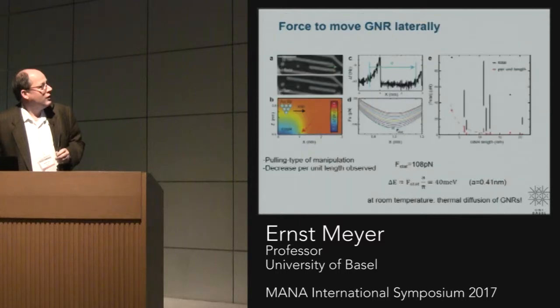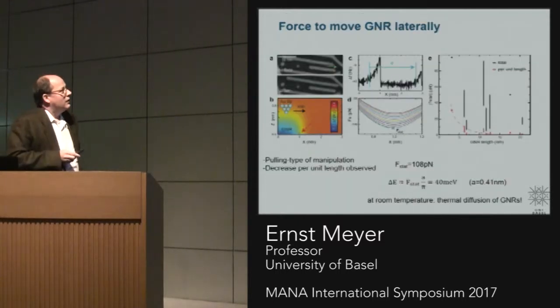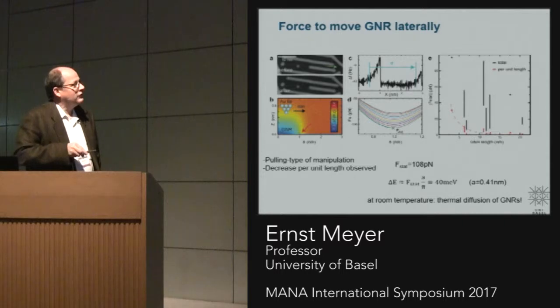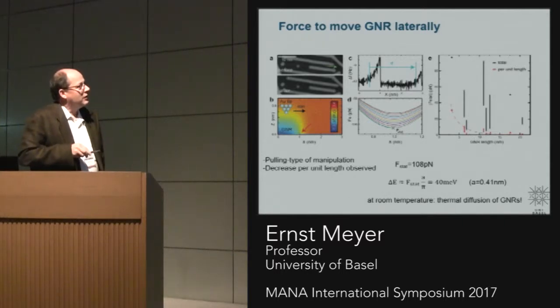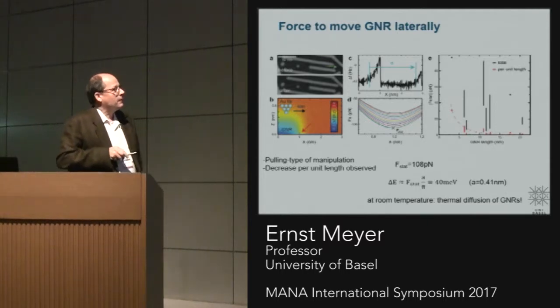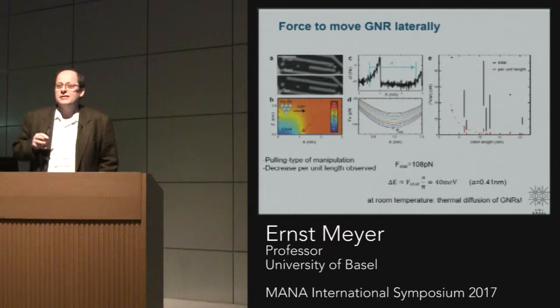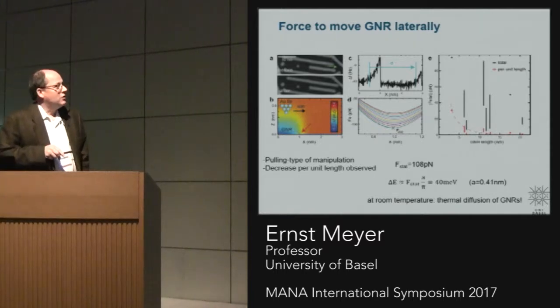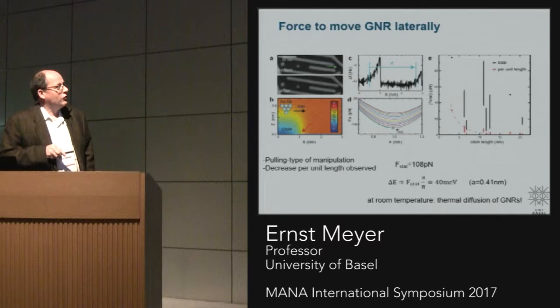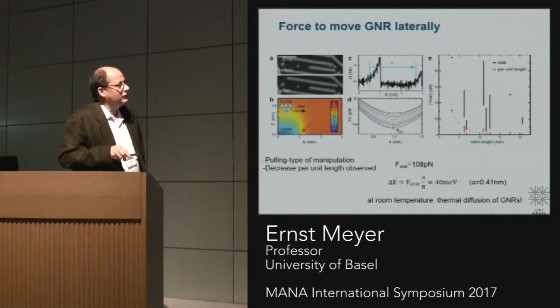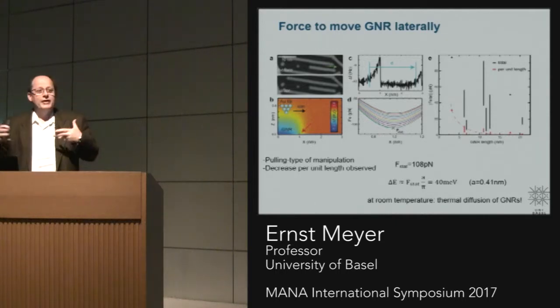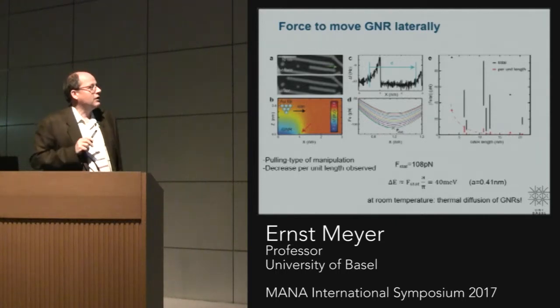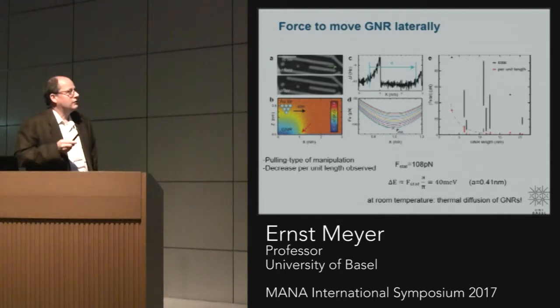It also moves, and now if you plot the forces here, which were determined by a method I will not discuss in detail, you see there is some scatter. The main thing you can say is actually it doesn't depend so much on the length, but if you plot the force per length, then you see it really decreases. So you see immediately these are red points here. So clearly it's really not depending on the length. So somehow there is something there still which resists, but it's not depending on how long it is.